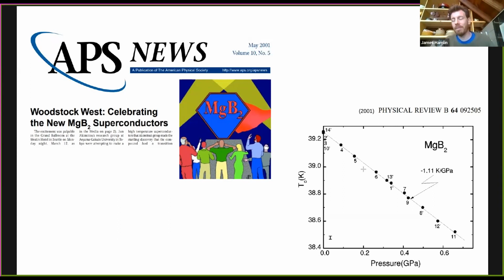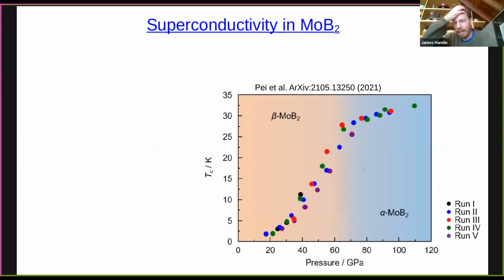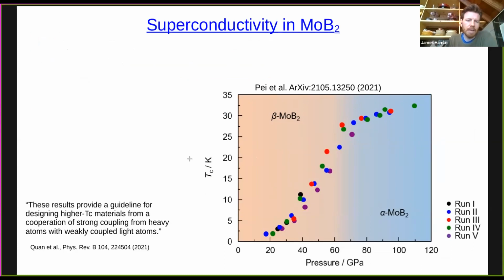And it turns out that it's very hard to substitute on MgB2, but anything you put into MgB2 causes TC to go down. So it's sort of a snowflake, or it perhaps appeared so until recently, this study that just appeared in 2021 showing that molybdenum diboride under pressure exhibits TCs as high as above 30 Kelvin. This phase at high pressure appears to be an MgB2-like structure. Although I will say that some work by Yundi Quan and Warren Pickett indicates that the superconductivity is really quite different in molybdenum diboride than in MgB2.